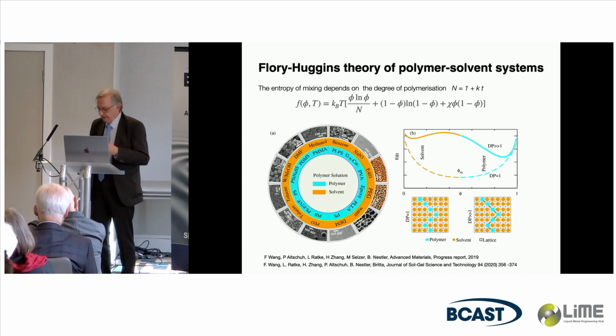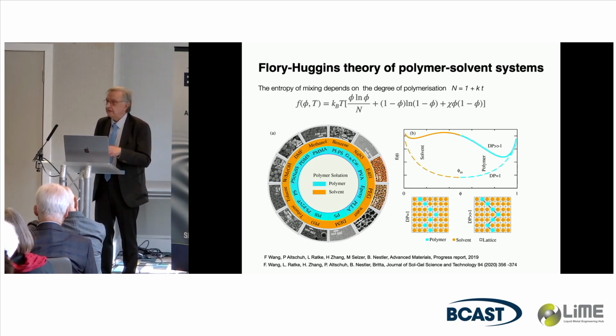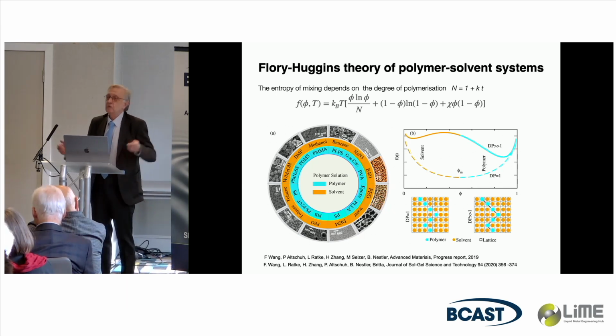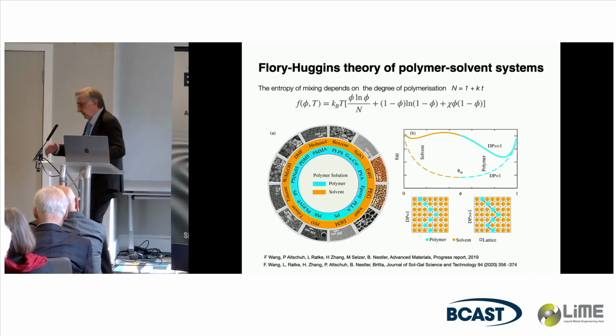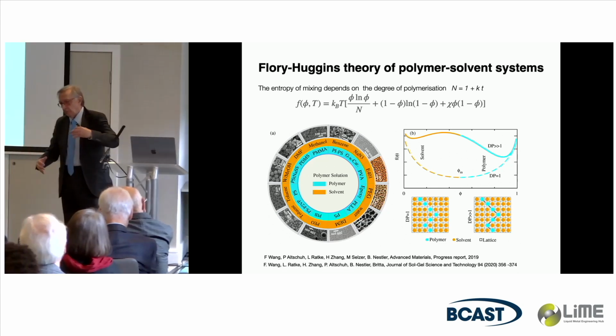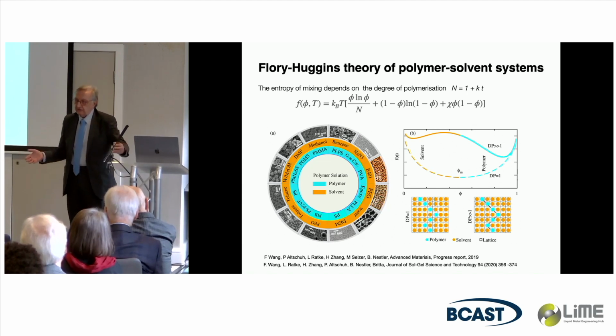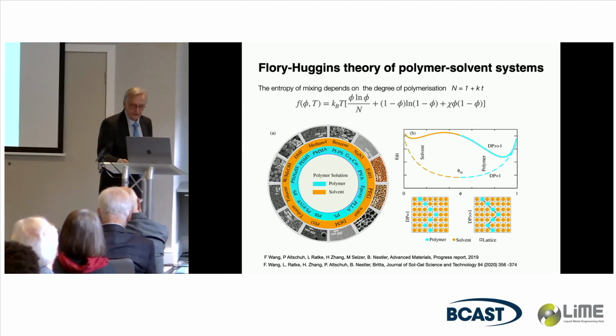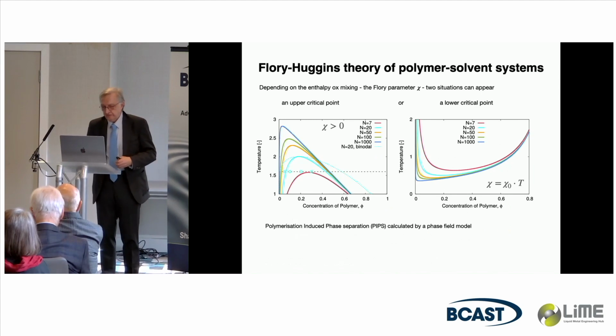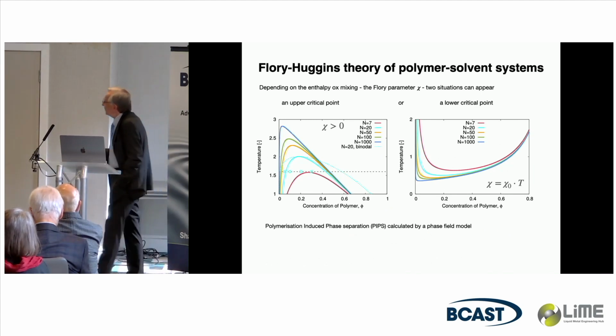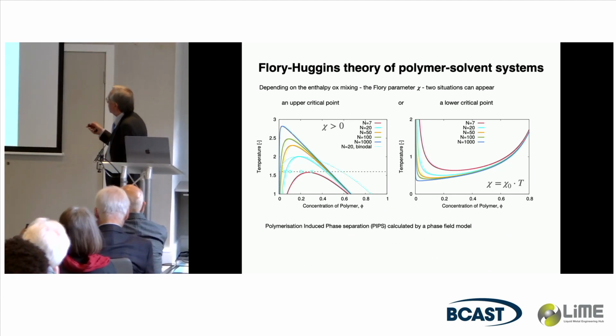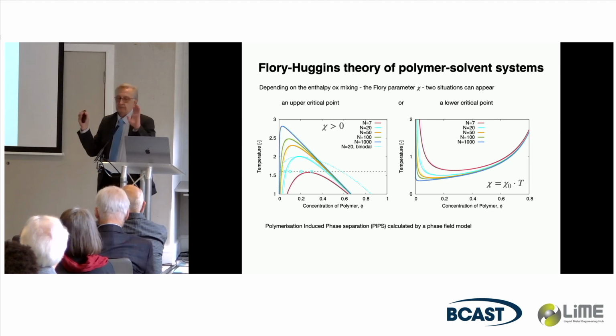To calculate that, go back to Smoluchowski's equation. This shows you exactly that. Or take Carothers' law, which says if you have a chemical reaction, the amount of material reacted defines the degree of polymerization. This is exactly the same. So the point is, we just made studies with an upper critical point and a lower critical point, just assuming that the Flory-Huggins parameter or the entropy of mixing is linear in temperature.